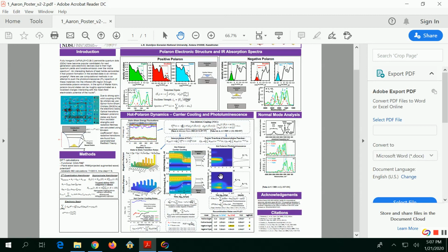Has this been applied to a system that has an experimentally determined quantum yield so you can get quantitative agreement versus qualitative? Right. So if you just consider interband photoluminescence, across the band gap, the computed yield is like 60%. And is that comparable? Yeah, in experiment they see anywhere from 50 to 100. So it's inside the band of the experimental data, I'm not aware.